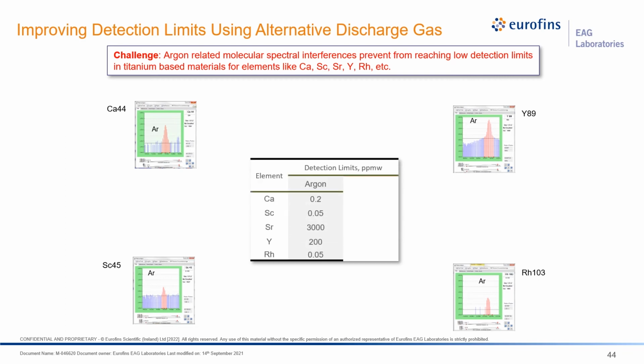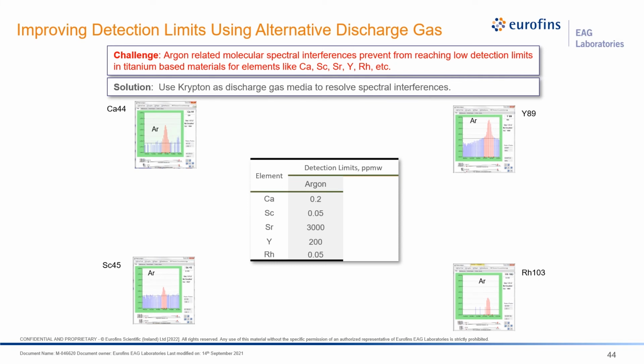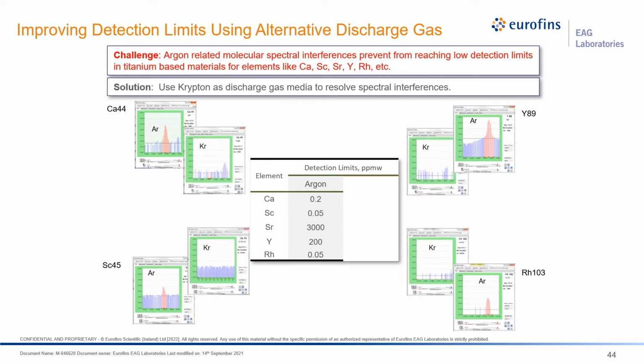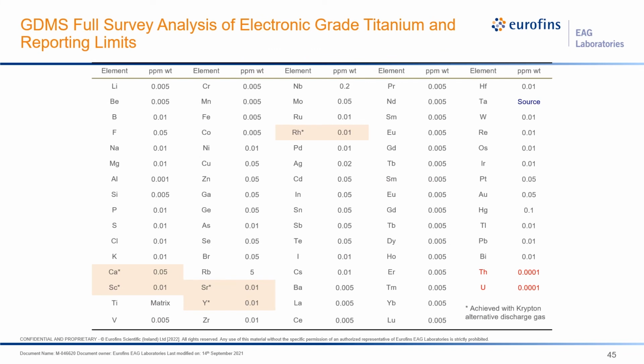Now, if we use argon gas, as you can see here, the limit of detection is very high. Now, if we use krypton as the discharge gas, can we resolve the spectral interference? The answer is yes. Now you can clearly see those mass interferences are gone. As a result, we have successfully lowered the detection limits by a couple of orders of magnitude. Here is the full survey analysis capability of GDMS on electronic grade titanium. You can see the reporting limits are from 0.1 ppb to 0.05 ppm. With krypton as the alternative discharge gas, the elements highlighted here have very low detection limits.